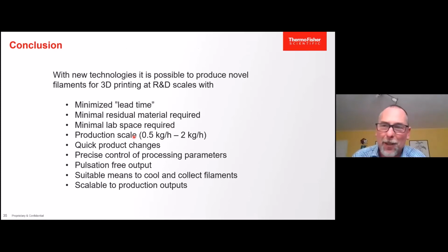Of course, it has its limitations. If you try to make 50 kilograms, you see, okay, it will take a day. But it's possible. Quick product changes. Processing parameters can be recorded. You can cool and collect the filaments. And what is important, it is scalable to production, because also in production, you have twin screw compounders of a similar design, of similar lengths. And so also you can use scale-up methods to create a process for these newly found filaments.